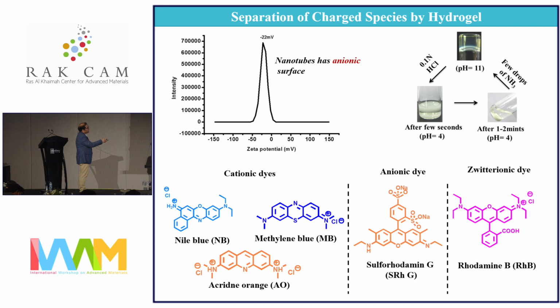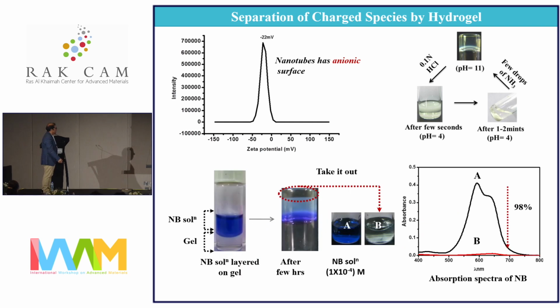The original pH is 11. If you add a few drops of HCl, the pH becomes 4, and it becomes a salt. With a few drops of ammonia, it can reform. So then we tried to make a gel chromatographic separation using this gel.